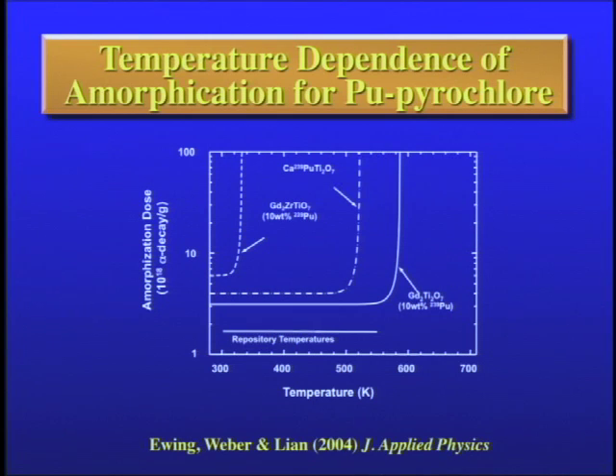Well, what we can do is now, here's the gadolinium titanate. We could add some calcium and plutonium, or we could add zirconium, and these are the curves for amorphization as a function of temperature. So if we put gadolinium titanate into a hot repository, it will simply accumulate the damage. There's not enough of a thermal pulse to anneal it. But if we change the composition and use the gadolinium zirconate with 10 weight percent plutonium-239, you can see that through most of the history of the repository, there would be enough heat to anneal out the damage.